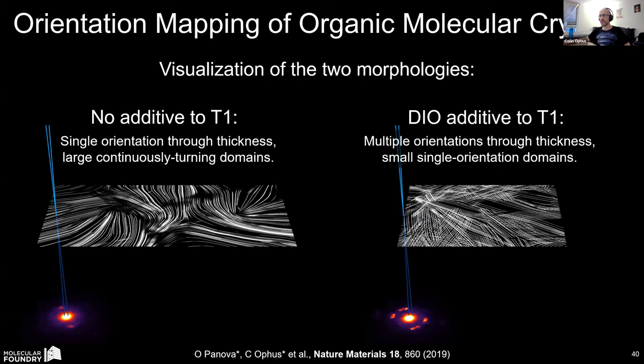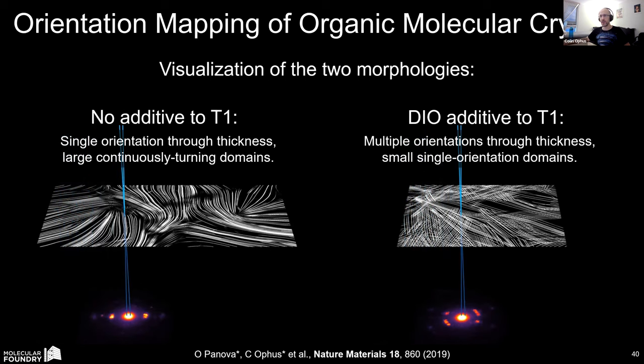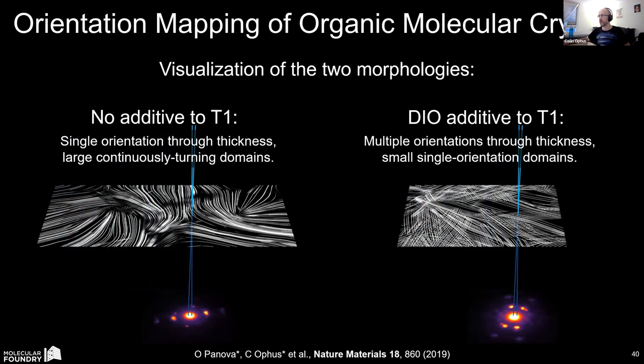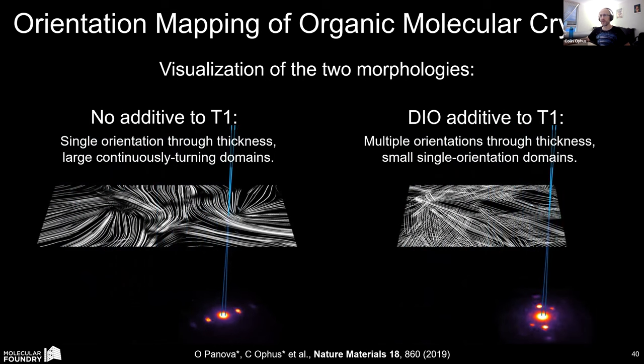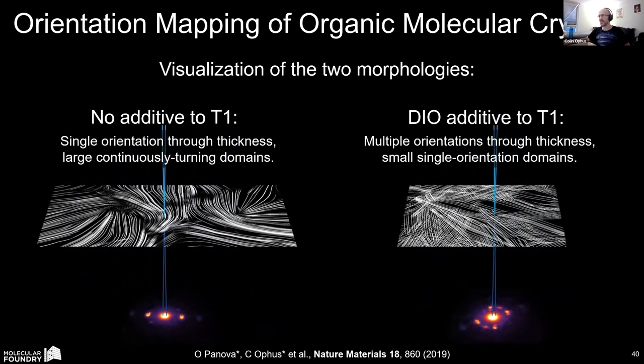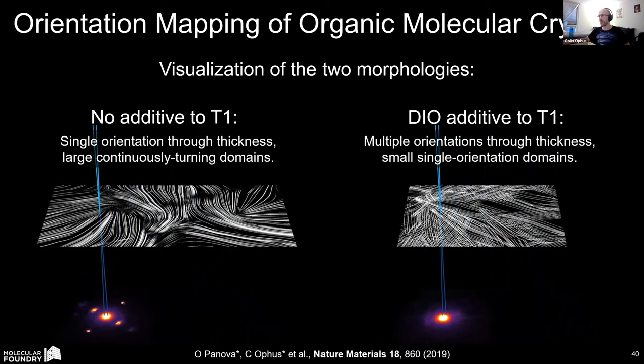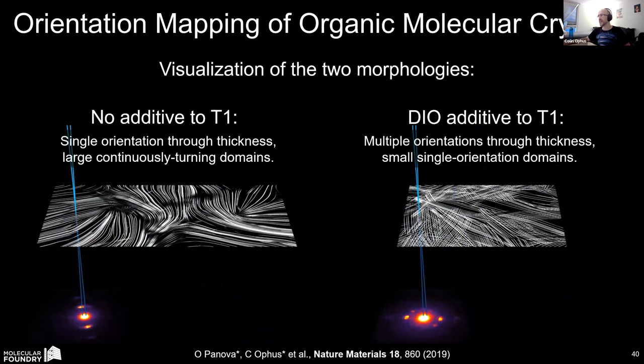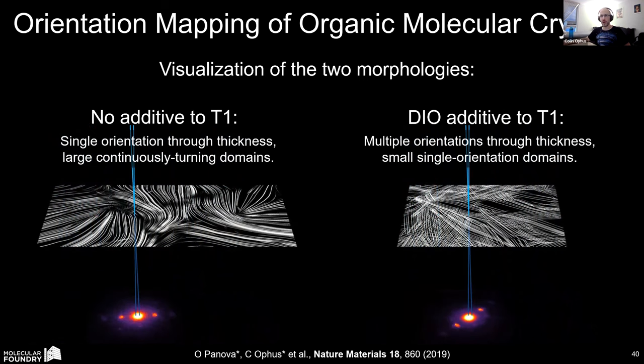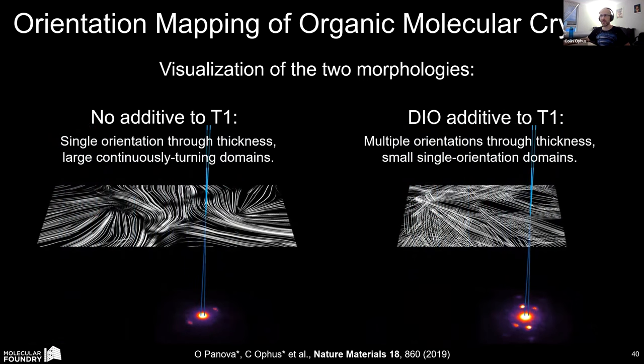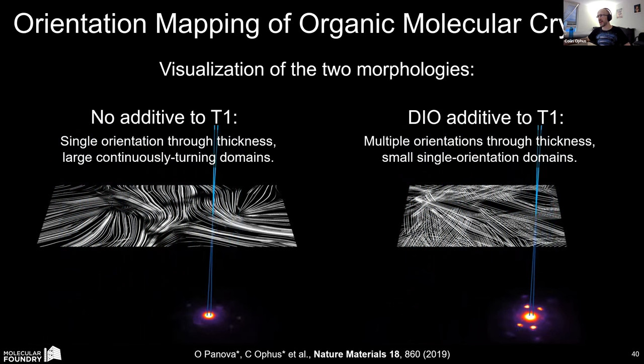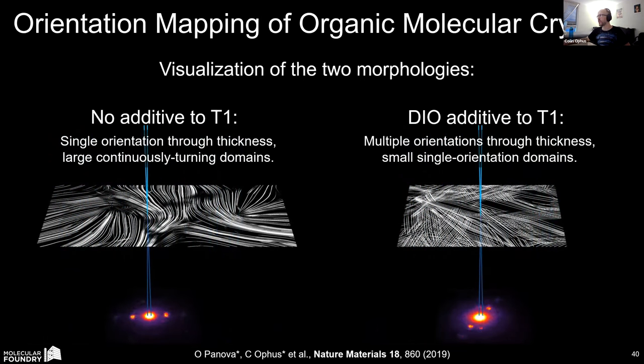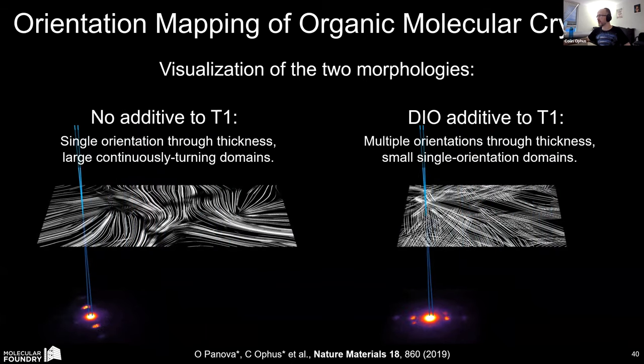So what do I mean? This is the T1 small molecule sample, the reconstructed morphology. And this is the same material, but adding a DIO additive to break up the grain structure. I'm just showing an animation here, scanning the raw experimental data below. You can see that if you don't have the additive, you have these large, continuously turning domains, and there are a couple of grain boundaries, but very much minimized. Whereas if you add the additive, it breaks up the material and you have a lot of overlapping crystalline grains and none of this continuous rotation. So the pi-pi mesostructure of this material is very strongly mediated by adding this additive.